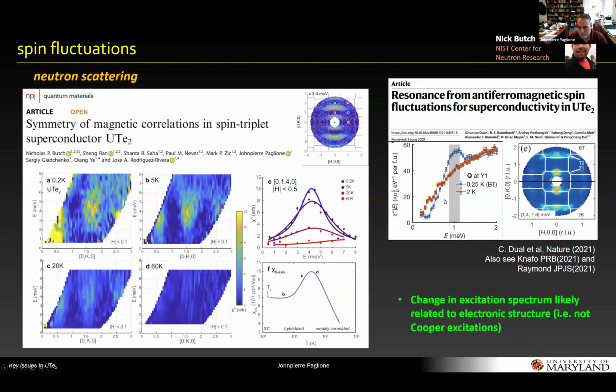Okay, so the simplest interpretation is that if you see some intensity, you assign it to a Q vector, which would imply that there's a propensity towards antiferromagnetic order, and Pengcheng Dai's group took this and also observed a resonance below the superconducting state transition and implied that this finite Q vector resonance was consistent with an antiferromagnetic spin fluctuation driving superconductivity in UTe2, which is interesting in the sense that there's no other known triplet superconductor that seems to be driven by antiferromagnetic fluctuations. Okay.